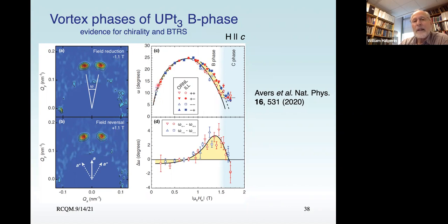You can see then that this onset of irreversibility, if you wish, for plus plus versus plus minus experiments, or minus minus versus minus plus experiments, start to deviate in the angle of the splitting when you go to fields which are of the order of 1 Tesla and beyond.